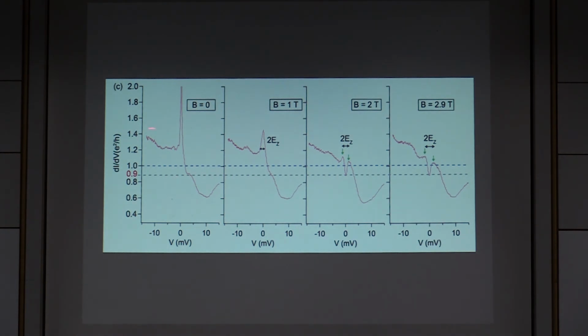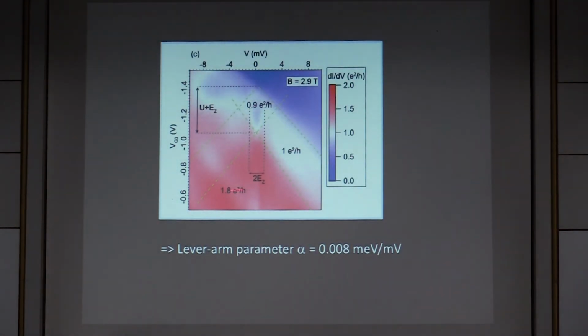So these measurements of nonlinear conductance show that at zero energy, if you sit in this plateau, in this 0.7 regime, you have an overshoot of the conductance due to superconductivity. But if you increase the magnetic field, gradually you see that you go towards a single peak in the conductance, and then this peak splits, as one would expect from the splitting of a Kondo resonance due to the Zeeman effect. And this is a measurement done at high magnetic field that shows clearly this splitting of the Kondo resonance.